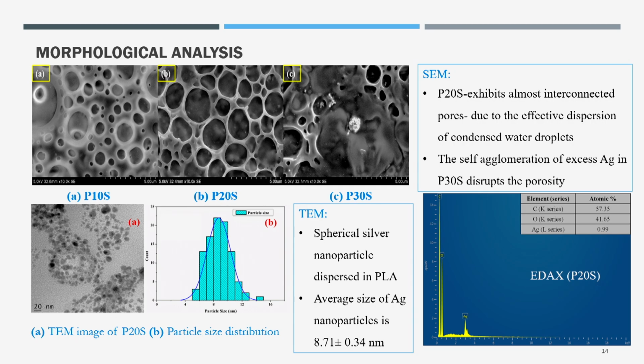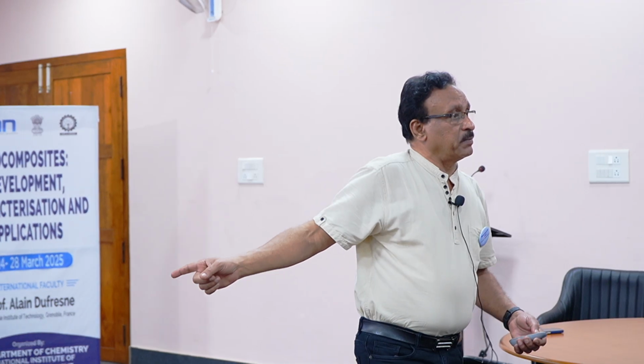And when you do that, all the particle sizes reach about the nanometer dimension. So 8.71 × 10^-9 ± 0.34 is the average size of the silver particles distributed within the system. And EDAX, what is called EDAX? Elemental detection.